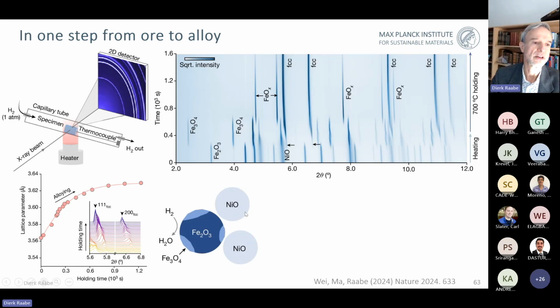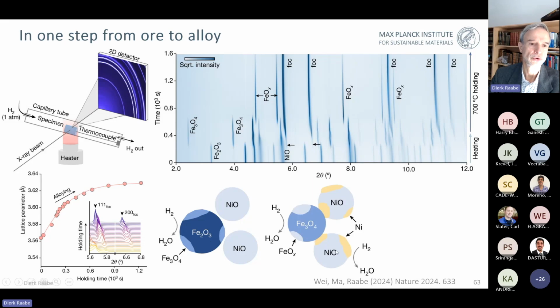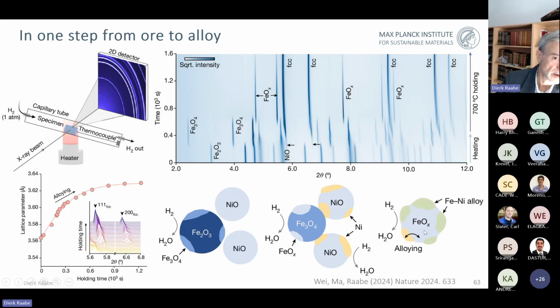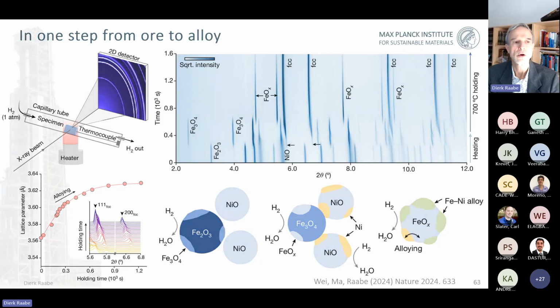That means we see here the nickel oxide. And then you have the first steps from the hematite transitioning into the magnetite. But as soon as the first nickel is formed here, you can see that these little yellow droplets, the iron, actually start to partition into these nickel areas, forming directly the iron nickel alloy. So the kinetic reaction pathways are different than what we thought, and that's quite interesting, and we look also deeper into that. So I stop here, and I thank you very much for bearing with me.